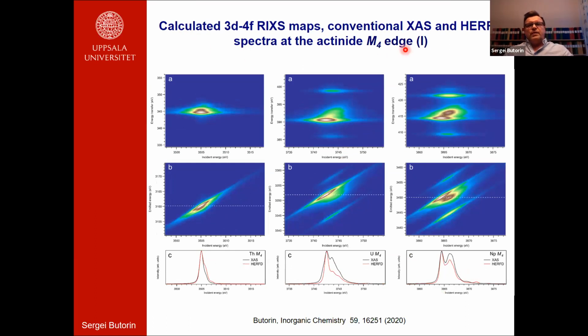The RIXS maps for the M4 edge, as calculated, are quite different from those at the M5 edges. In particular, here you can see two groups of transitions, here and here, which are quite a few eV below and above the main structures. And these are, again, the final state effect due to 4f-5f exchange interactions. So it's very easy: you just switch off these integrals in the calculations and these structures disappear.